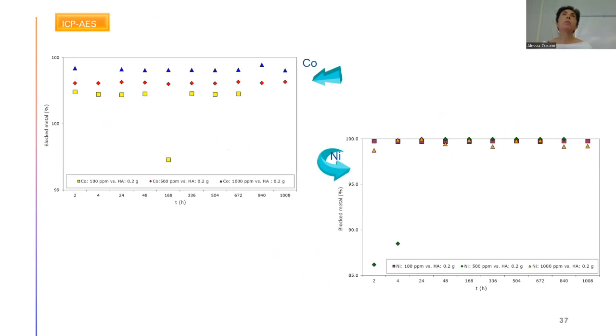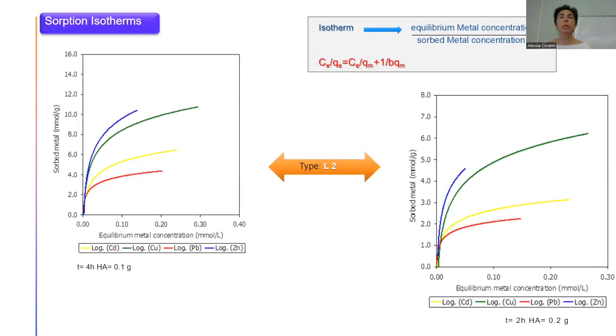So from 100 ppm to 1000 ppm as a concentration of the two elements, with a time between 2 hours and 3 weeks. And they show the same behavior. 24 hours is the best immobilization that we could have. So then, after all these studies, we start to study the sorption isotherms according to the Freundlich isotherm.